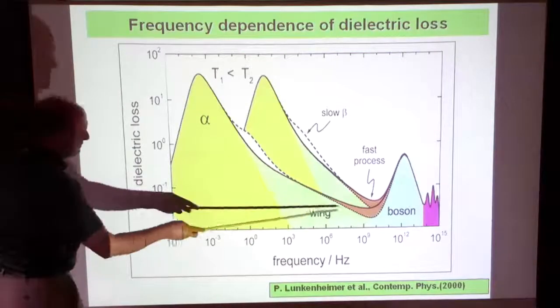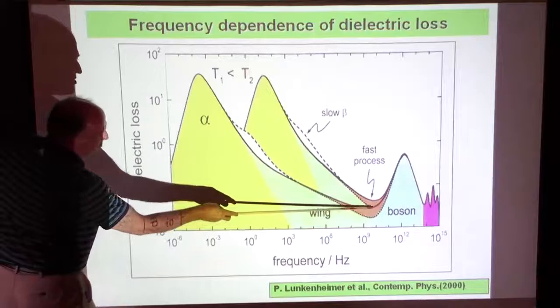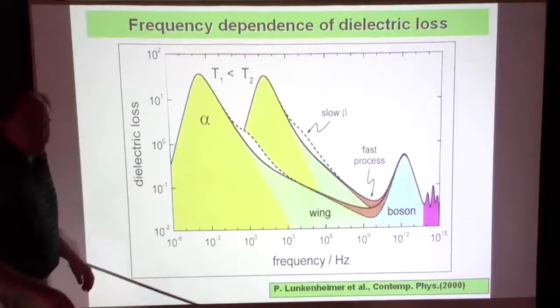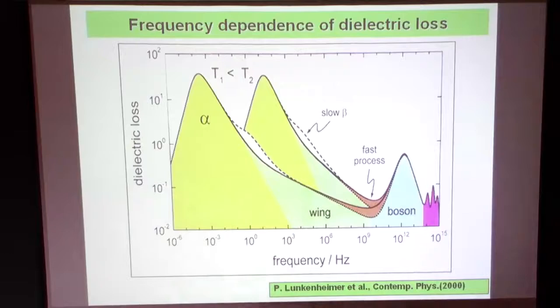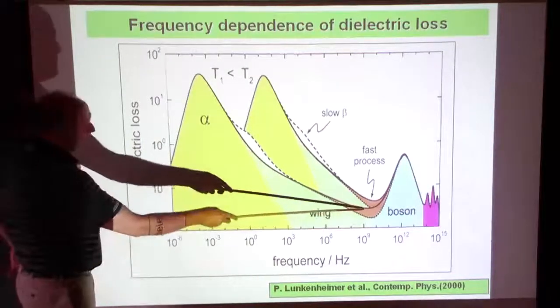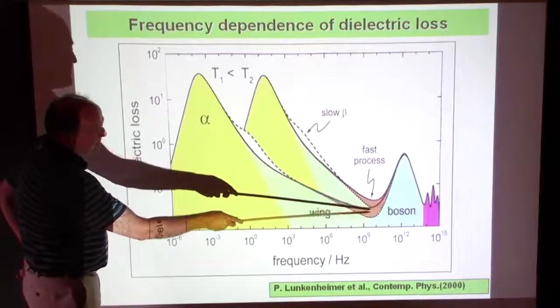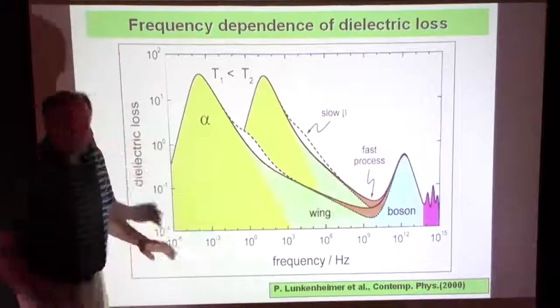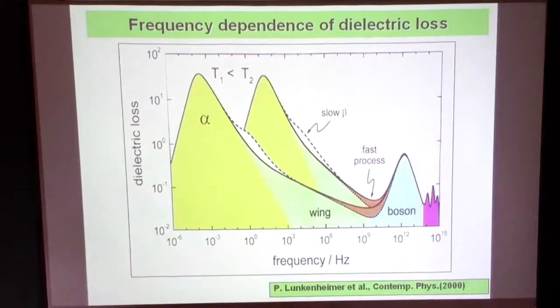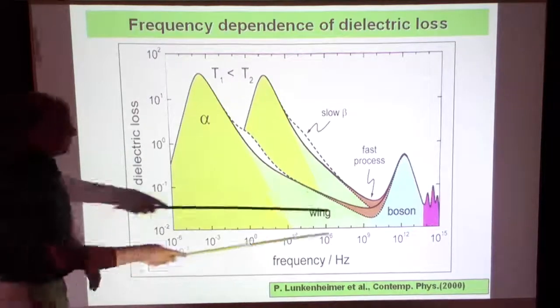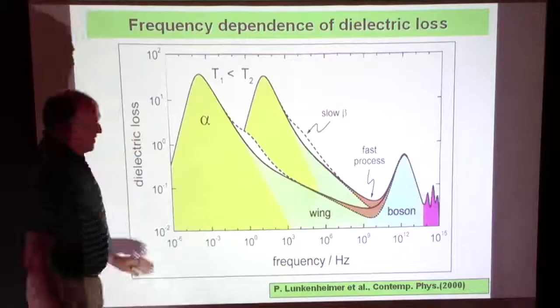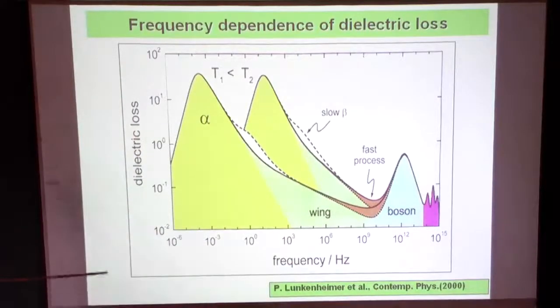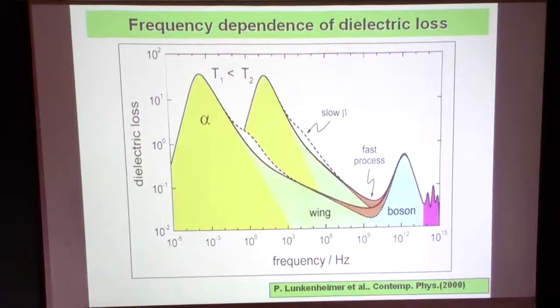And then there are even higher frequencies, which we call nearly constant loss or fast processes. This is cage breaking in the systems described by the mode coupling theory, or predicted by the mode coupling theory and then found later on experimentally. And then we have the boson peak, which is something like the remembrance of the system to vibrations, to something which you could call phonons in a crystal. And this purple at the end doesn't interest us today. This is just the internal intermolecular vibrations in an organic liquid, for example.